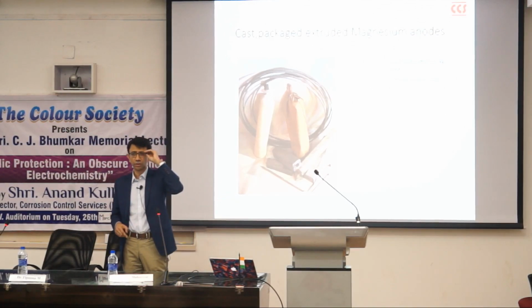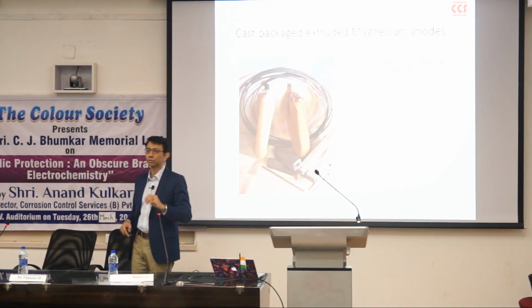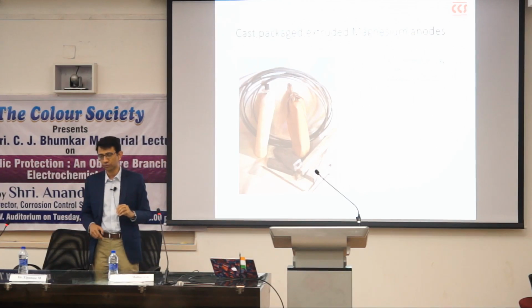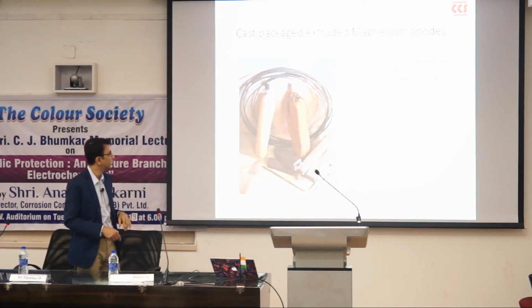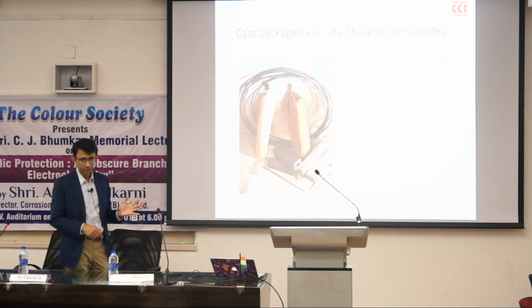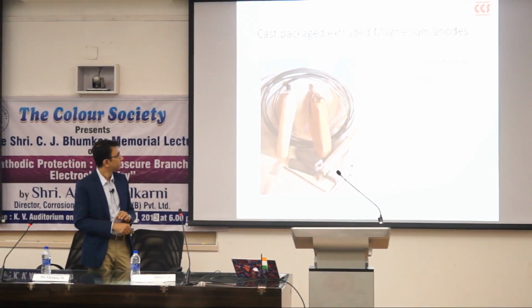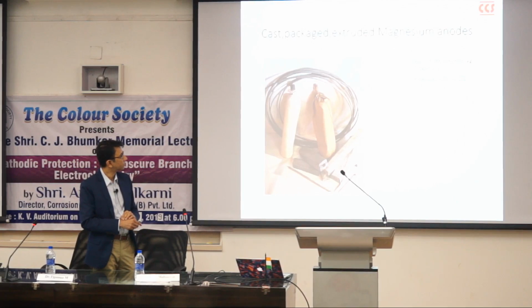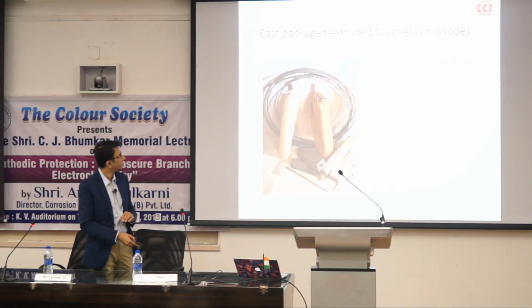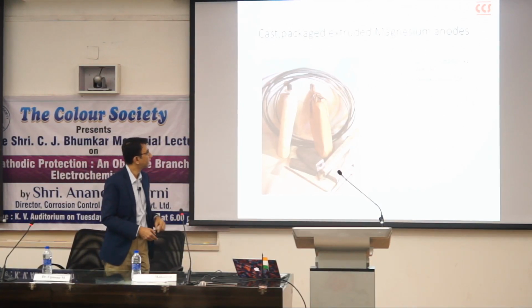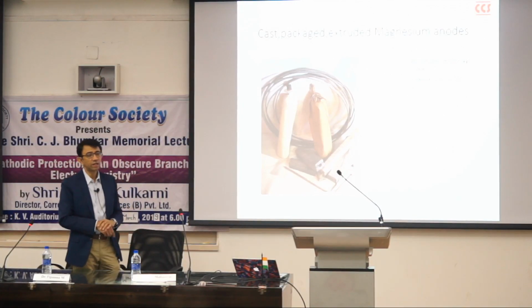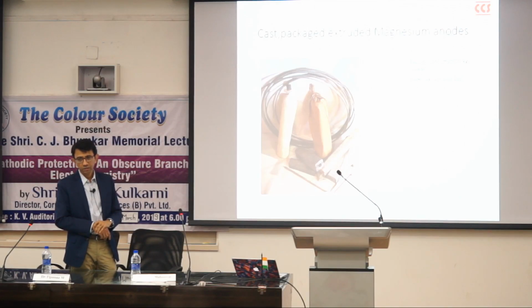So, it is the most frequently used anode for galvanic protection of steel structures, buried steel structures. If you have chlorides in the environment, it doesn't act like an anode anymore, so you don't use it for marine applications. And its rate of consumption, this is again wrong, this has got wrongly added because this is the aluminium thing, but anyway, the rate of consumption is about 8 kilograms per ampere year. So, that is again lower than zinc.